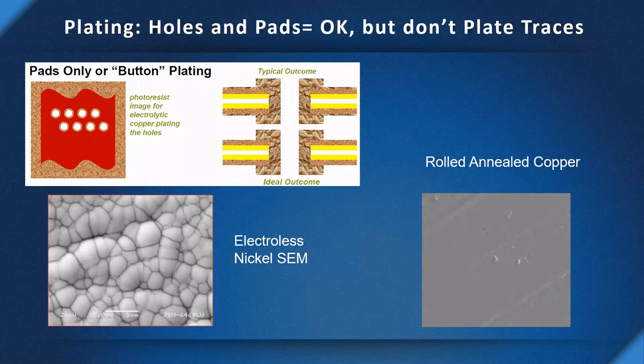Electroless nickel builds up in nucleation sites, and then you have these grain boundaries, and I have an image on the lower left. If you bend that structure, it'll crack and then transfer the crack into the copper trace underneath. Once again, the folks that build these circuits would definitely steer you away from putting the metal plating in those areas. It's totally fine to put it on pads and surface mount lands where there's going to be no bending, but you want to keep that out of the flex areas, and you want to keep that off the traces that travel in a flex transition zone.